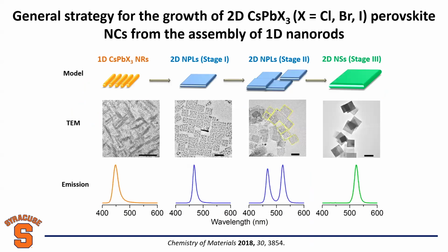Now here, I'll just quickly give you the results. Indeed, when we introduce the mixture of ligands, we tune the surface energy. We can make one-dimensional nanorods. Then we transfer to an autoclave and apply pressure. We can make square-like nanoplatelets. Interestingly, as we further increase the solvothermal reaction time, these small nanoplatelets can further assemble together by lateral fusion and Z-direction stacking, and can form larger nanoplatelets and even big nanosheets.